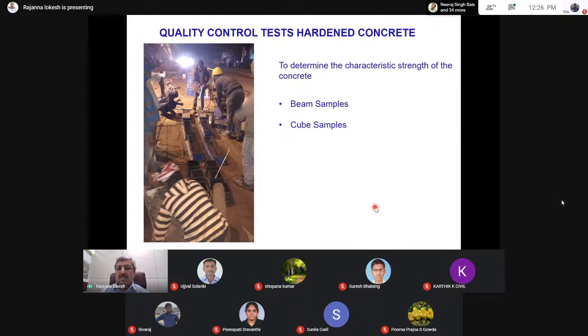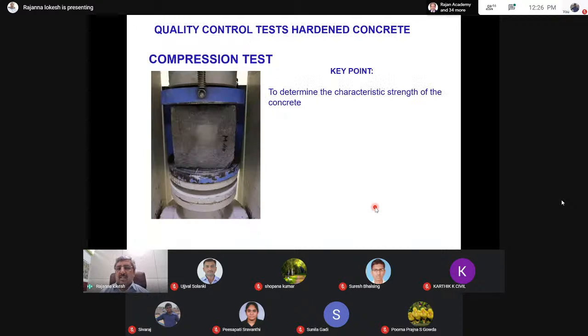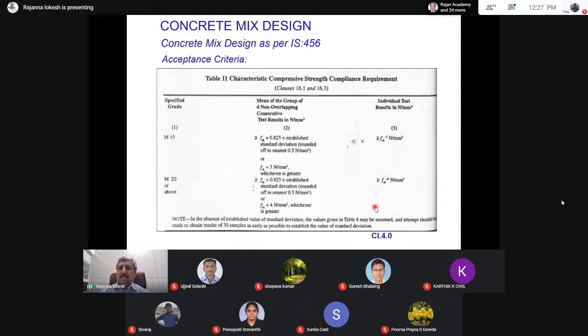So these are the concrete cubes that will be cast at the site and then later tested. So, compression testing on cubes. This is the acceptable limit. Within the project, we can also have our own standard deviation if we are not able to get a standard deviation for a single project. So the acceptable criterion will be something like fck + 4. Suppose our grade of concrete is M40, the acceptable requirement is 44 MPa. So any cubes tested for compressive strength should yield 44 MPa.